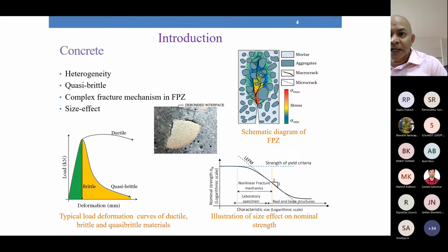Okay, and one of the most important aspects of concrete is that it shows a size effect. Meaning, if you look at this figure here, on the vertical axis we have the nominal strength, and on the horizontal axis we have the characteristic size, or some kind of a representation of the size of the structure. So here we have a horizontal line depicting the strength criteria or the yield criteria, and we have this sloped line, which is the linear elastic fracture mechanics behavior. So when you have a small concrete structure, it follows the strength criteria, but large structures follow the linear elastic fracture mechanics.